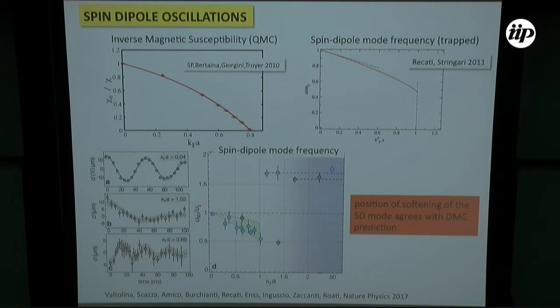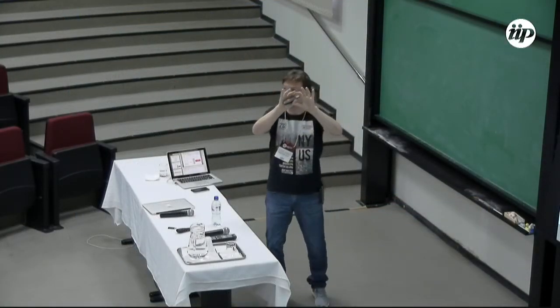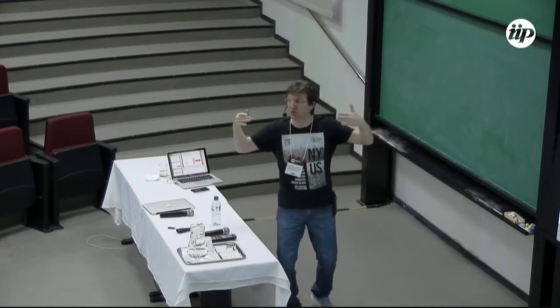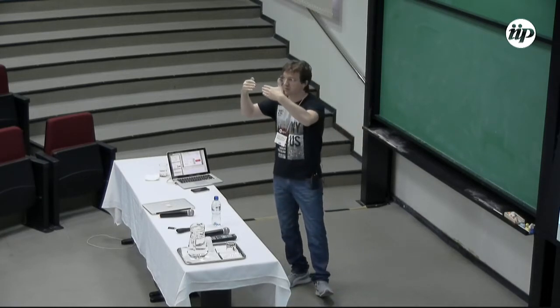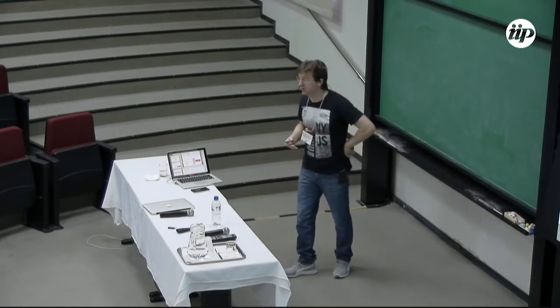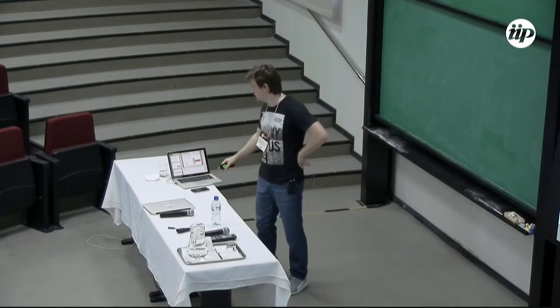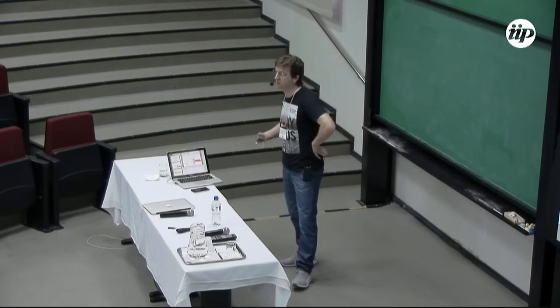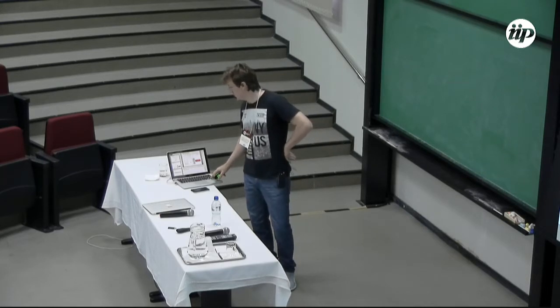And they've seen that this frequency decreases as a function of the interaction strength. But at some point, it jumps up when the repulsion is very strong. And what happens here is that the two clouds remain stable in the fully ferromagnetic phase. So the two clouds do not start merging at all. And this frequency corresponds to the frequency of the two clouds oscillating by hitting against each other. And this critical point corresponds very well with what the quantum Monte Carlo simulations predicted. So here we can say that despite the fact that we have to use this fixed node approximation, it seems that it's a good enough approximation to describe this kind of ferromagnetism.